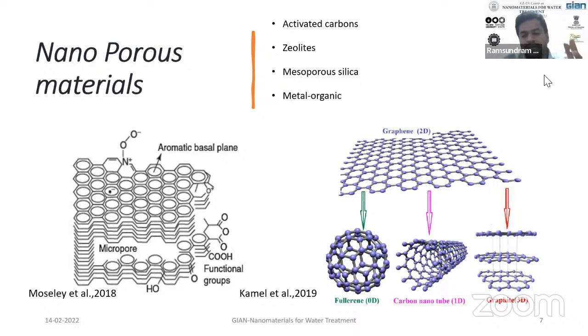And the stability of the 2D layer or the 3D layer is based on the resin that has been used for encapsulating or making the final layers, or joining one layer to the other layer, where you have a resin in between. If that resin is not working properly, then it is going to get dissolved. So this is what was understood from the quoted literature, and we tried in our labs to have monolayers of graphene and just tried it. The performance was very good. Initially, when we tried with graphene, the surface area was somewhere around 2,600 square meters per gram, and it was able to treat the water up to the desired level.